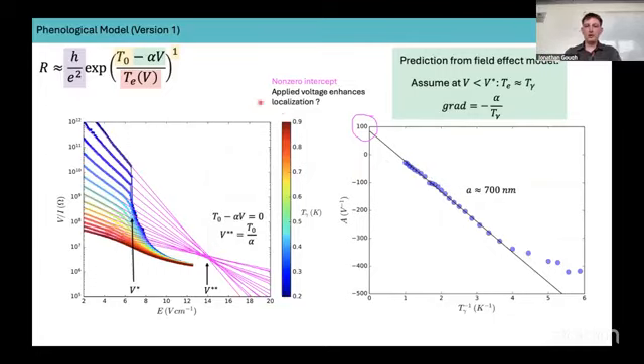One thing we're still working on in this area is that we have this non-zero intercept. It's very clear here, which suggests another voltage dependence that our simple model doesn't account for, perhaps a voltage dependence of this prefactor.